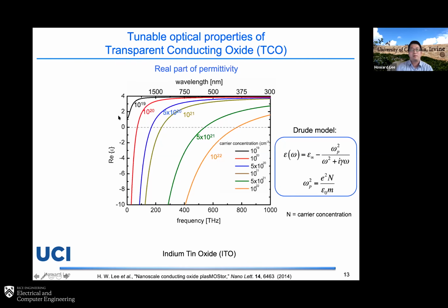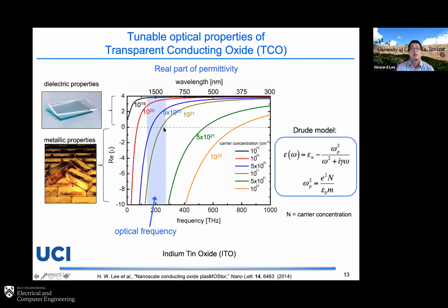And you look at the permittivity against the frequency or the wavelength of light. Depending on the carrier concentration of the material, you can have different dispersion, and you can shift the dispersion to shorter wavelength if you increase the carrier density. At the same time, at an optical frequency, for example 1.5 micron, you can have a dielectric property, meaning a positive permittivity, or a negative permittivity, meaning a metallic property, depending on the carrier concentration. That means it's really good. You can tune the property of the material by just tuning the carrier concentration.